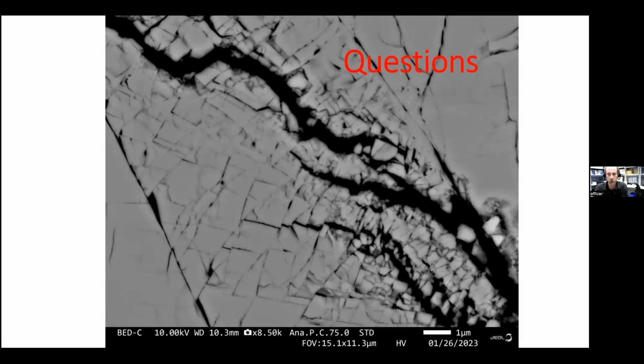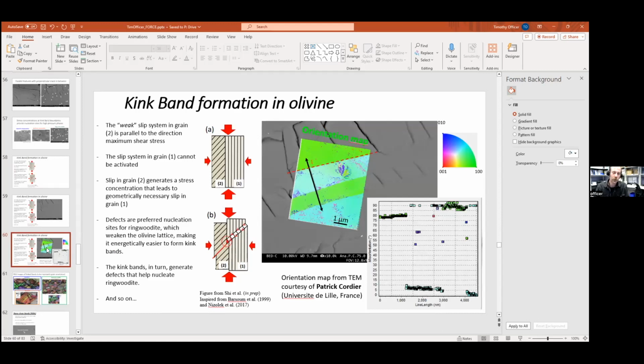Yeah. I'm glad you asked that, because you can see there are tons of slides I cut out because I knew I wasn't going to have time. So I didn't talk about the silicate data. But in terms of TEM, if you look at the grain orientation, we didn't get very good bright field TEM to see the high pressure phases. But one thing that we see are kink bands.